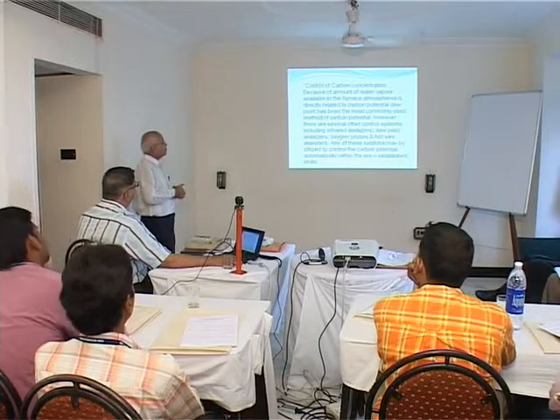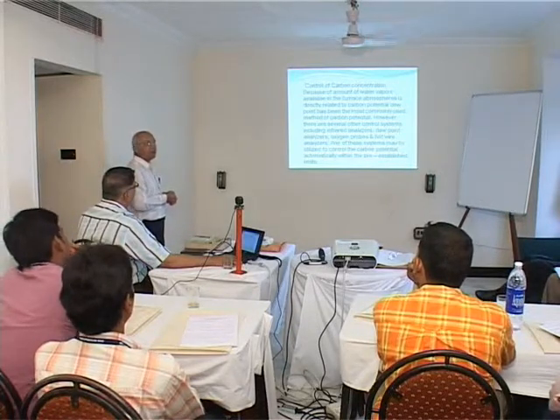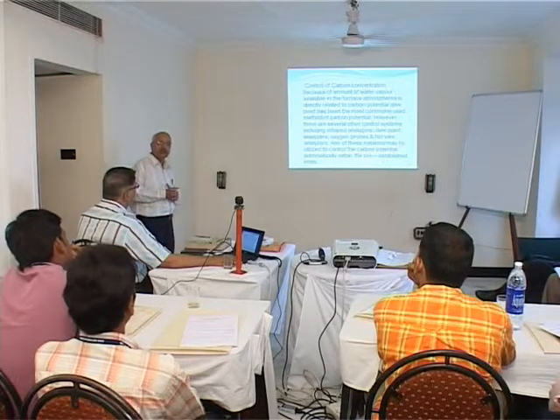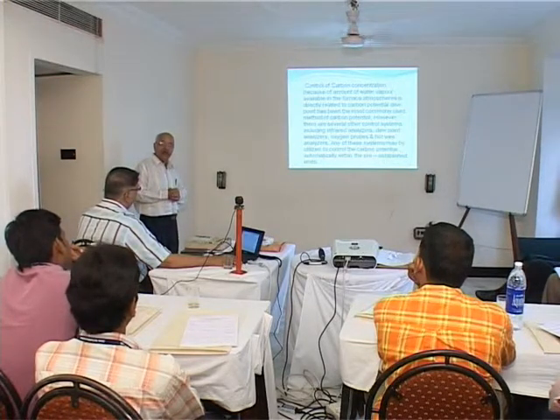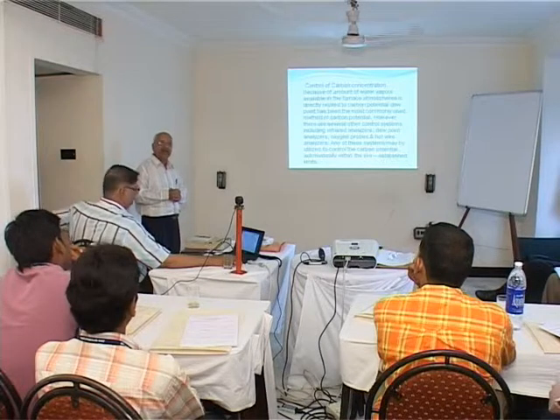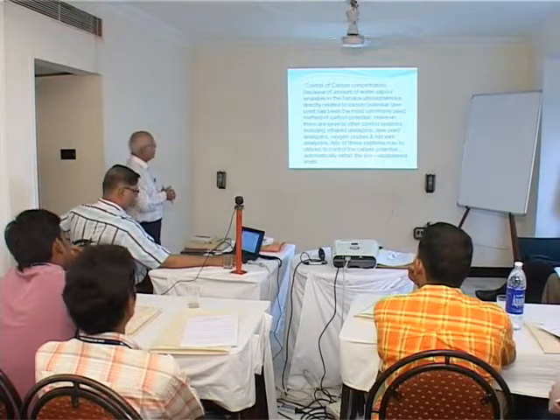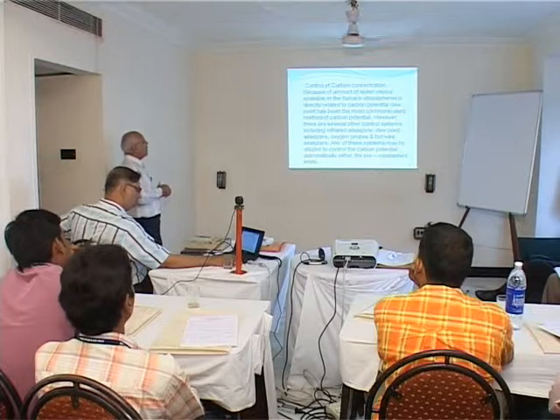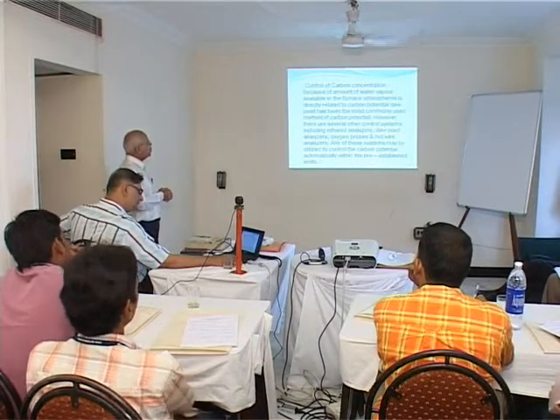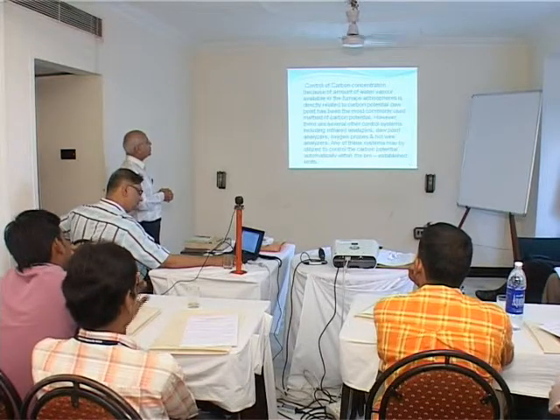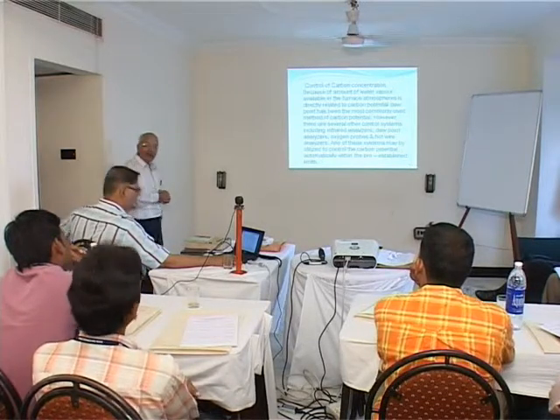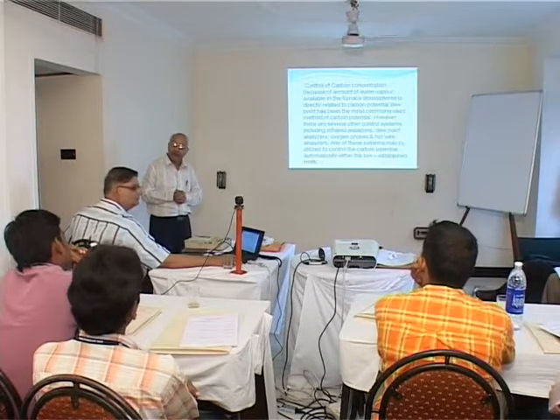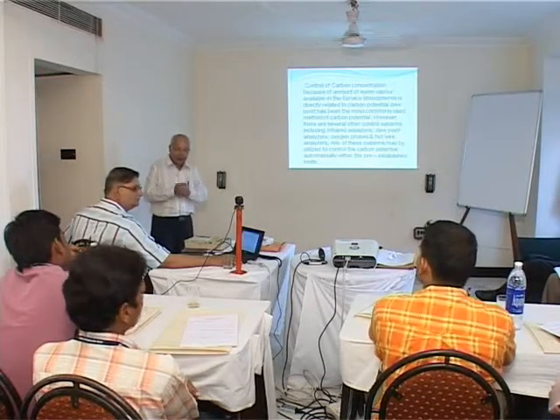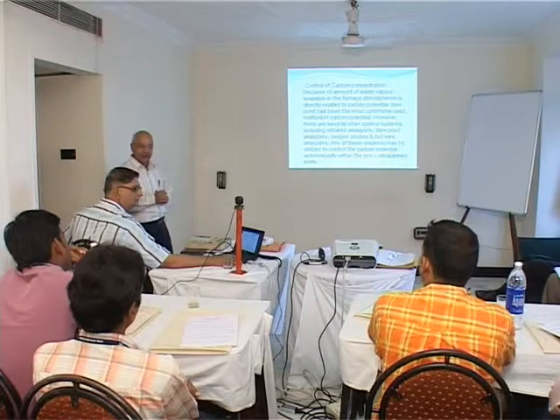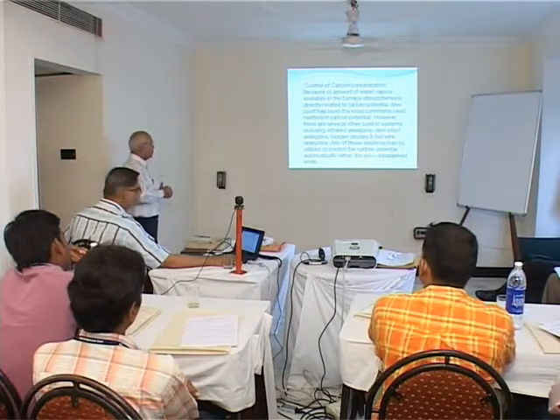While doing this operation, control of carbon concentration is very important. If the carbon concentration goes above 0.8, normally you get cementite in the network, which is again injurious to the health of the steel. Because the amount of water vapor available in the furnace atmosphere is directly related to carbon potential, dew point has been the most commonly used method for carbon potential. Anybody is doing gas carburizing? You are doing? Okay. Are you maintaining this dew point? You are maintaining. Very good.